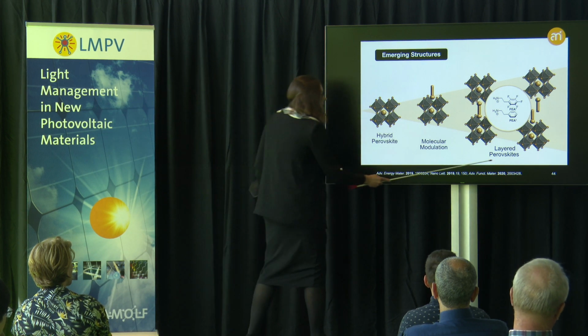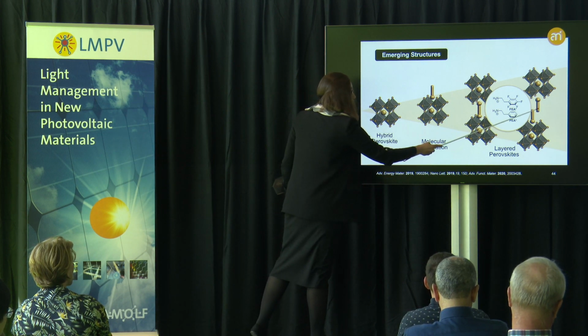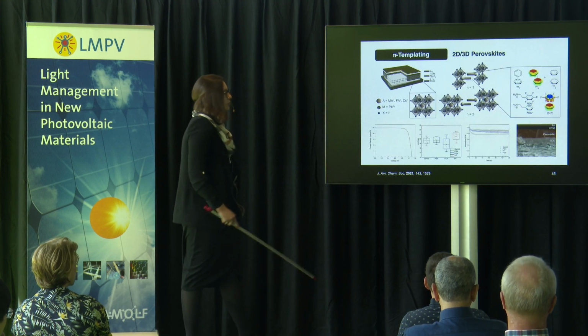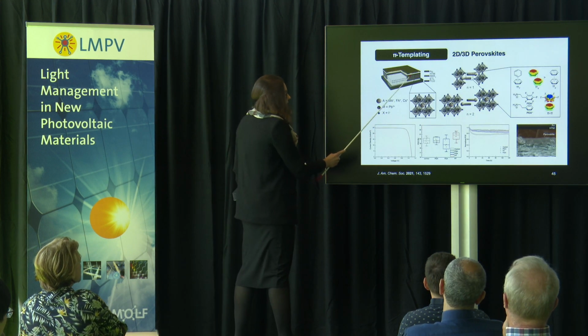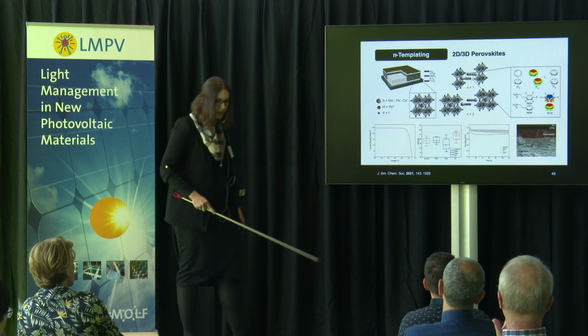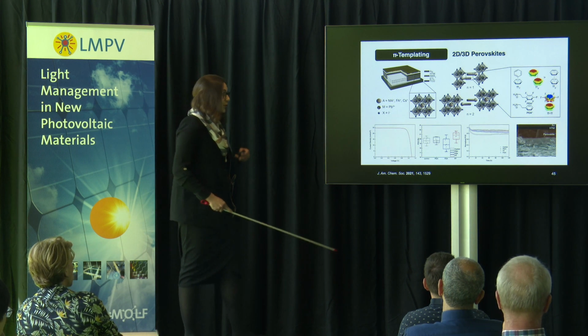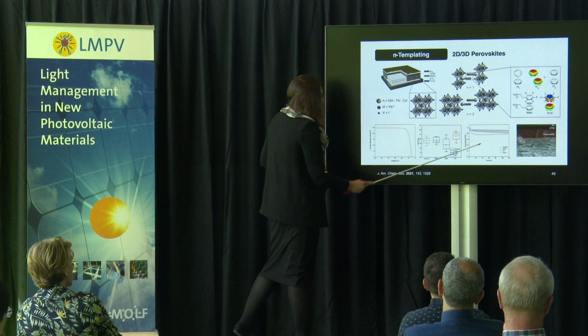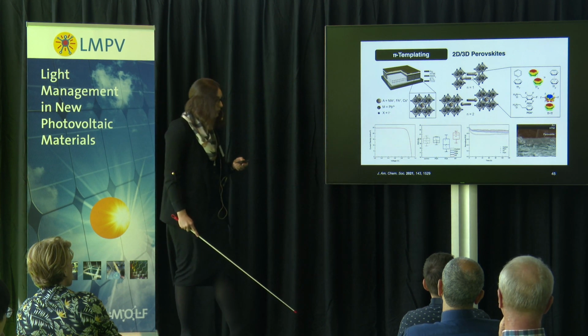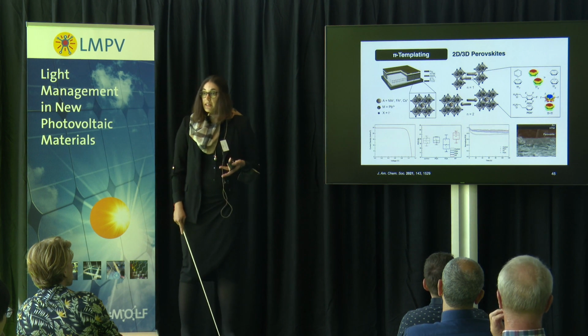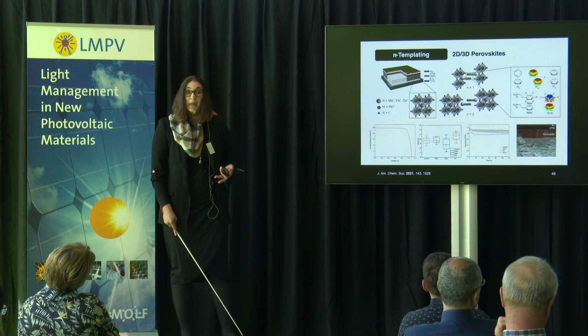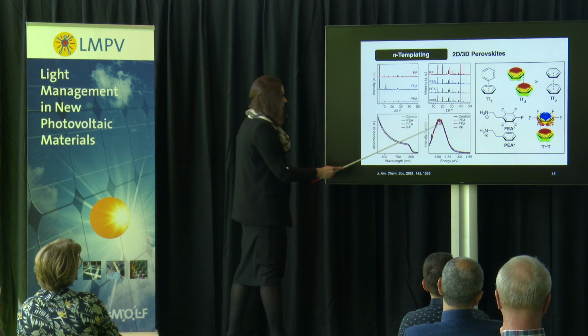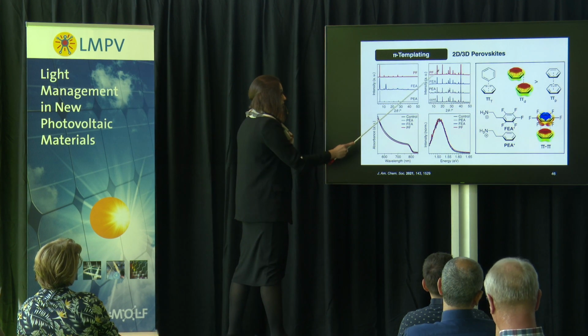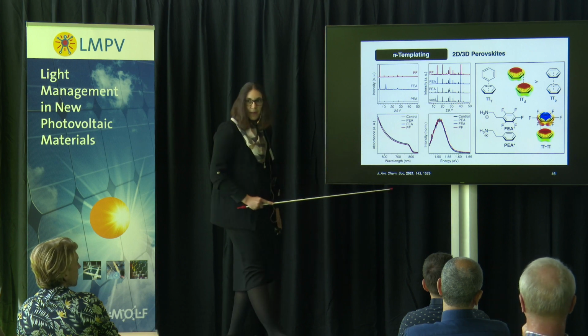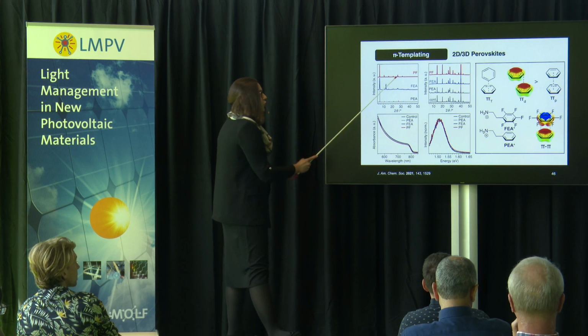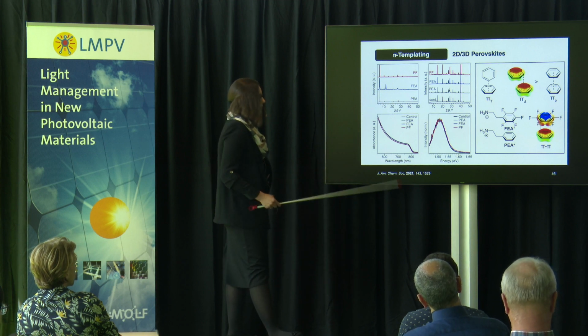the case of these layered two-dimensional perovskites or more stable phases, typically used in functional devices as, again, interlayers on these three-dimensional perovskite architectures, enabling them to further maintain these stabilization factors while also reaching competitive photovoltaic performances. This is primarily ascribed to the capacity of these systems to maintain the beneficial optoelectronic characteristics of these systems, as well as their three-dimensional structure, despite the capacity of all of these spacers to really form well-defined two-dimensional perovskites.